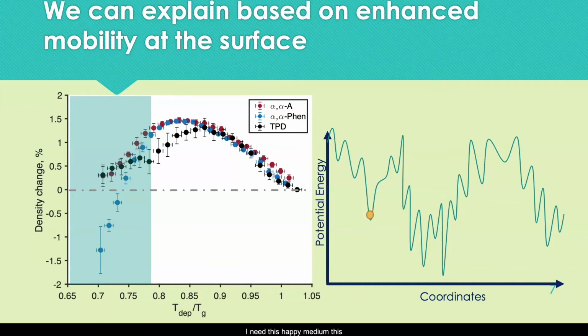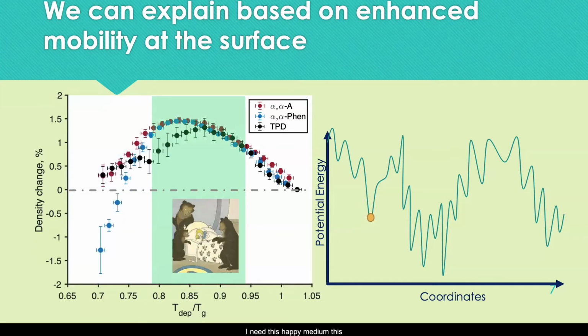So what I need is this happy medium, this Goldilocks region between 0.8 and 0.9 Tg, where the system has the thermodynamic driving force towards a lower state and is also fast enough to sample a number of configurations and find that lower energy state.